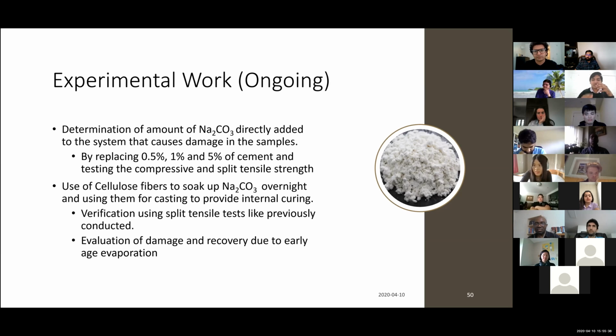Currently, in that test I used 5% by volume and tested it for compressive strength. It led to a huge 40% reduction in compressive strength when I tested it directly. What I read in the literature previously is that the carbonate part itself starts reacting with the alite and belite in the cement, and that affects the hydration itself. I'm not really sure what the sodium ion does, but the carbonate ion itself has a huge degrading effect if it's put directly into the mix.